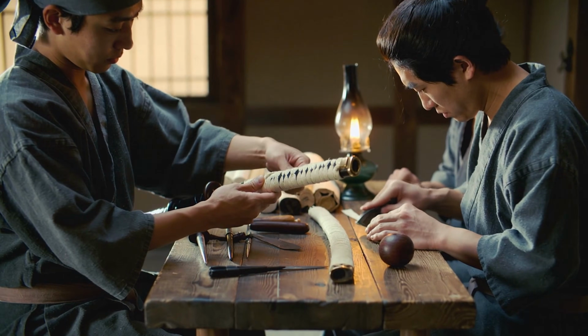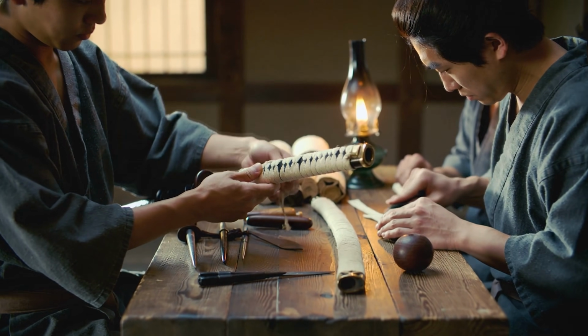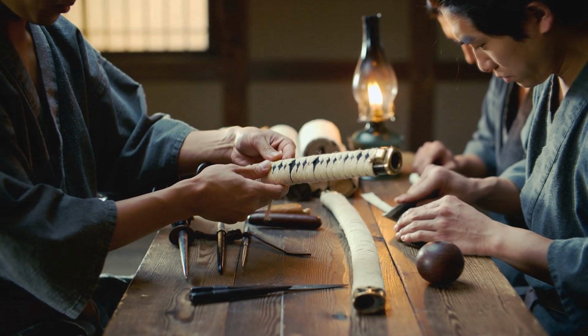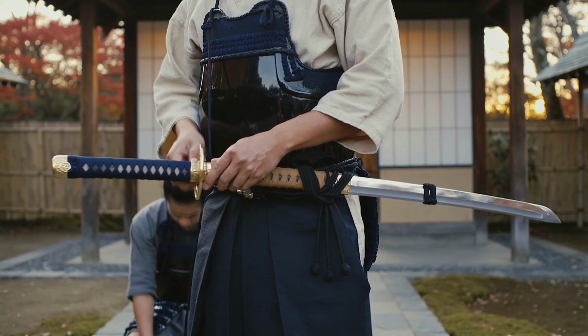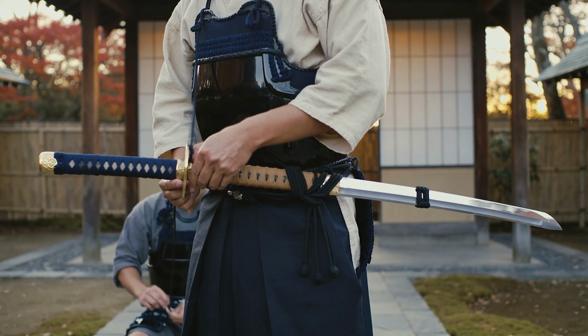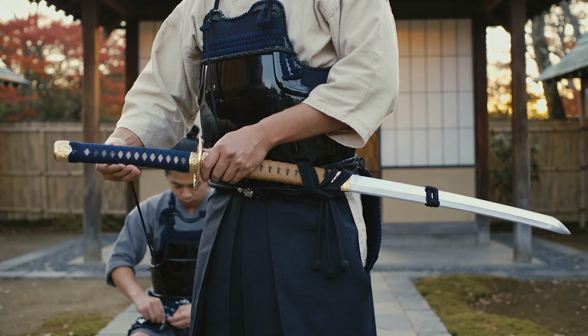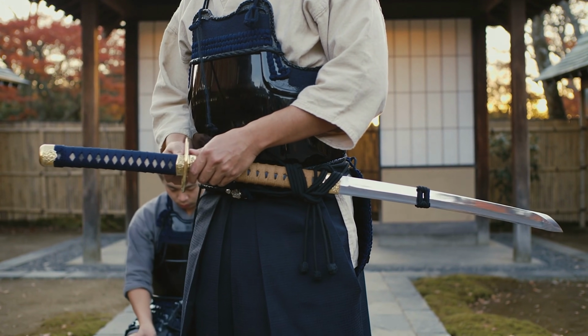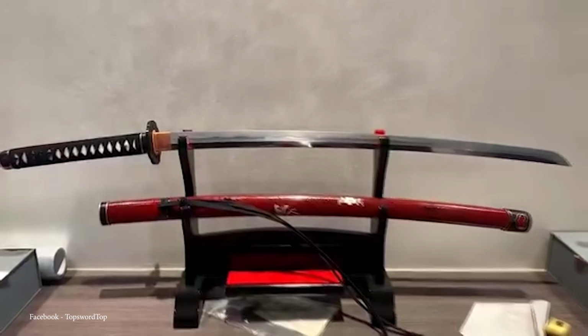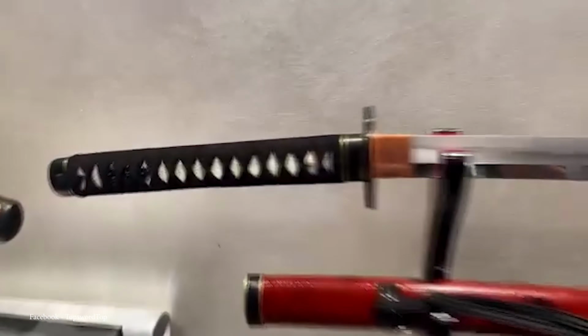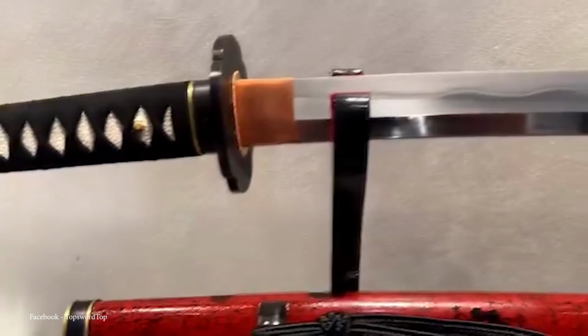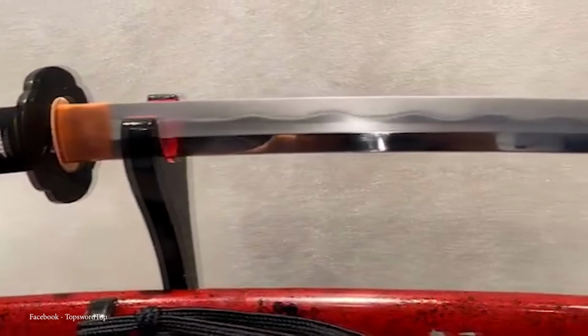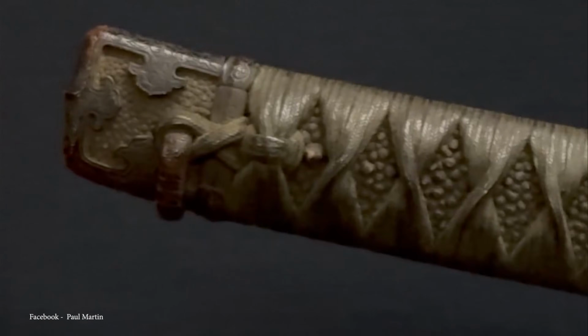Smiths also practiced laminated construction, such as kobuse, the hard steel jacket over a softer core, and occasionally a 3-layer configuration. These techniques produced strong, flexible blades that resisted breaking. Early examples from the Yamato and Bizen schools exhibit refined grain patterns resulting from careful folding, and contrary to later popular belief, folding was used to homogenize the steel, not create any decorative surface,